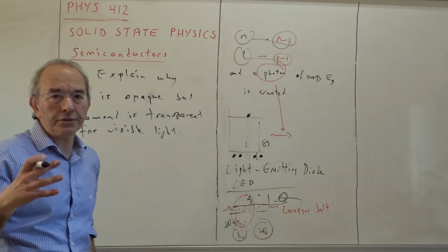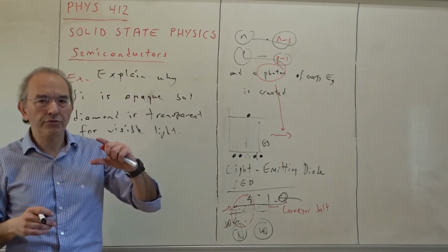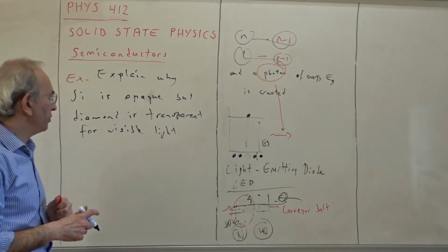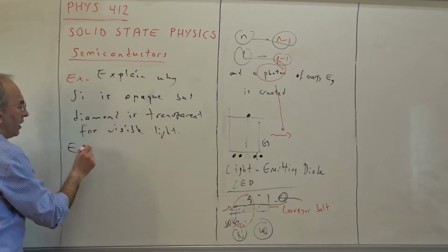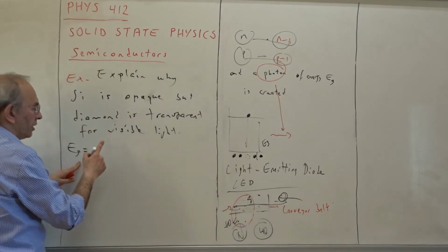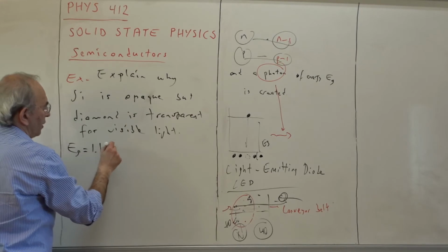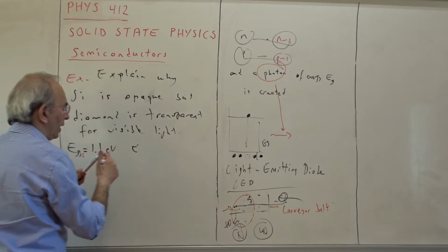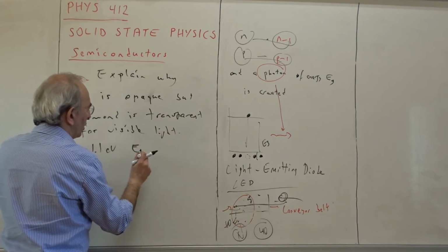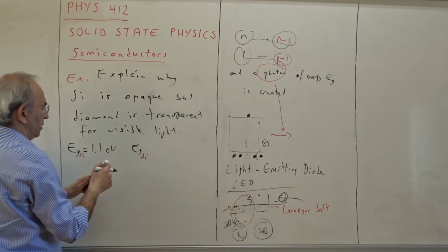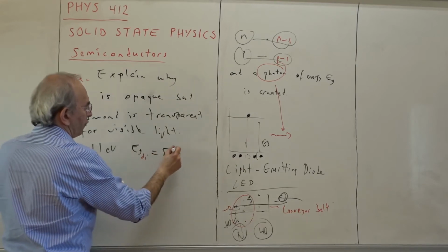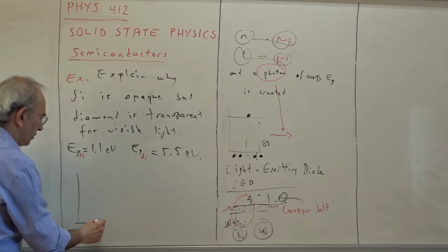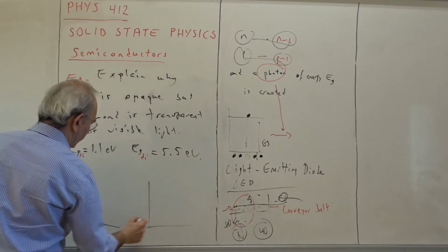Now we need two parameters, of course, as you expect. They are both the band gaps of these two types of materials. Eg that we have seen a minute ago for silicon, 1.1 electron volt, and this is for the silicon, and Eg for diamond, this is around 5.5 electron volts. So this is the picture for one, this is the picture for the other.